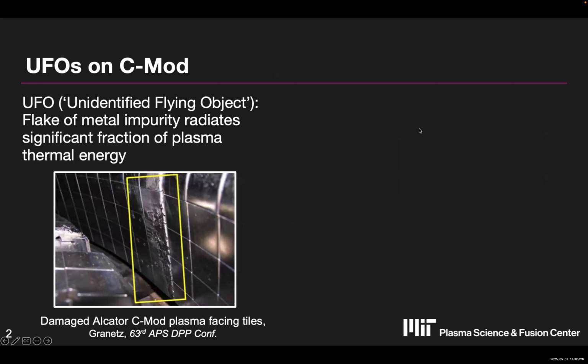So one type of disruption in tokamaks is called a UFO disruption. In fusion, UFOs don't have anything to do with flying saucers. Instead, they mean a flake of a metal impurity, usually from the wall, like tungsten or molybdenum, as others talked about, that could flake off and fly into the plasma, and that'll radiate a lot of power, so much so that it could radiate a significant fraction of the plasma thermal energy away and lead to a disruption. If you're operating a machine, you might see a glowing speck of metal fly in and enter this kind of transparent plasma, and you'll just see it pop like a balloon, as Xander showed.